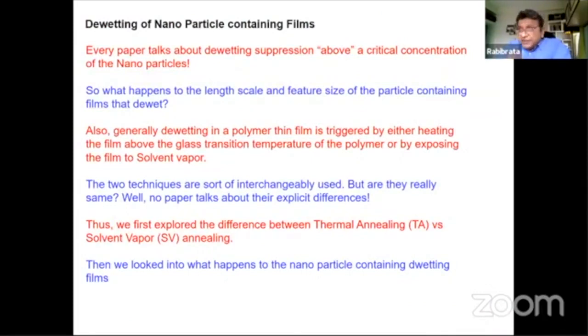However, for such films, the dewetting can also be triggered by exposing these films to solvent vapor. That's another very, very standard route. So what happens when you keep such a film in a solvent vapor chamber, the solvent molecule starts penetrating into the film, right? Because this is a good solvent for your polymer. So the film swells, and it is believed that the viscosity reduces because of the solvent penetration. Probably there is a little bit of swelling. And as a consequence, the glass transition temperature drops below the room temperature and the film eventually evolves.